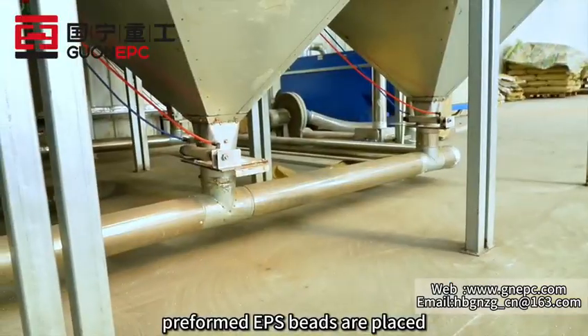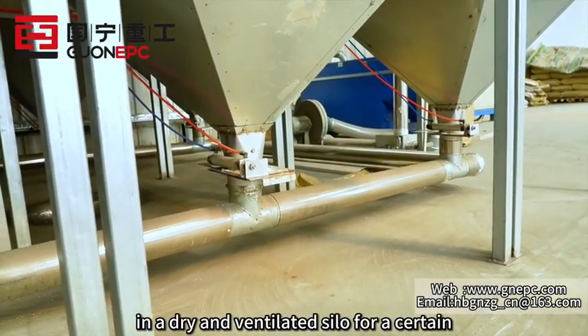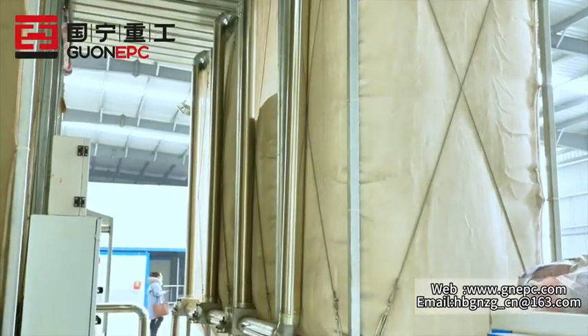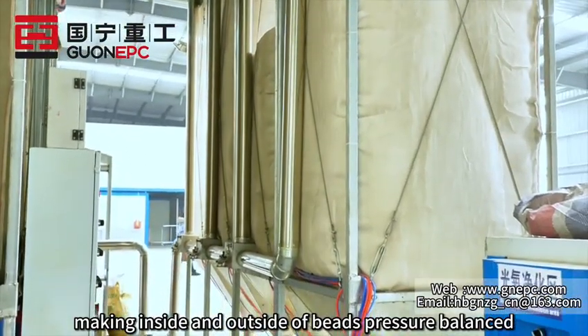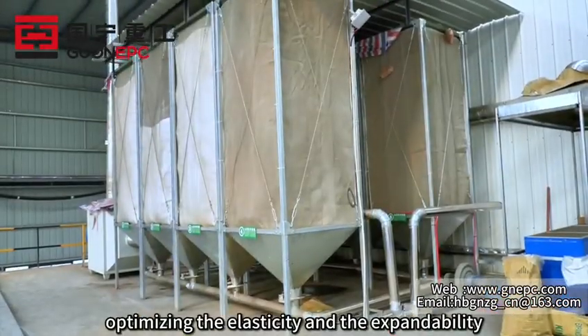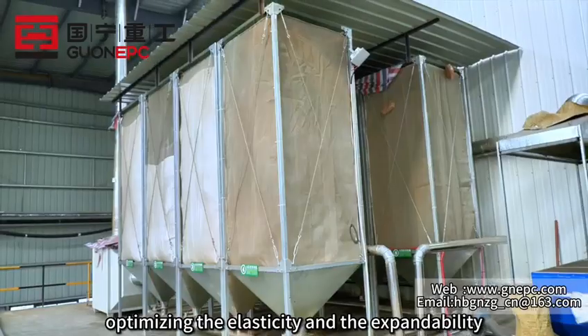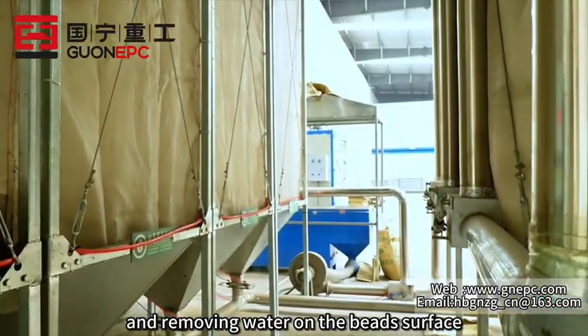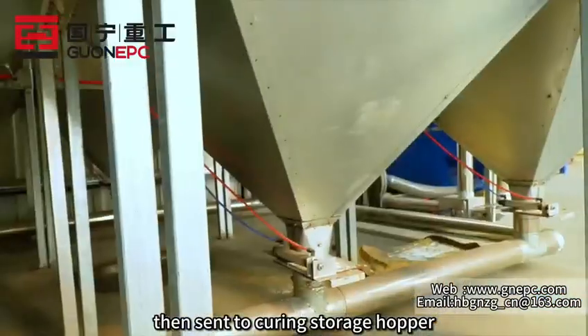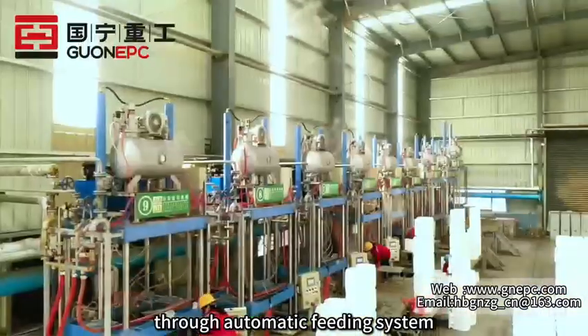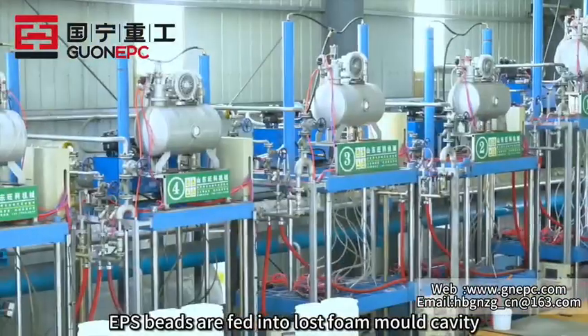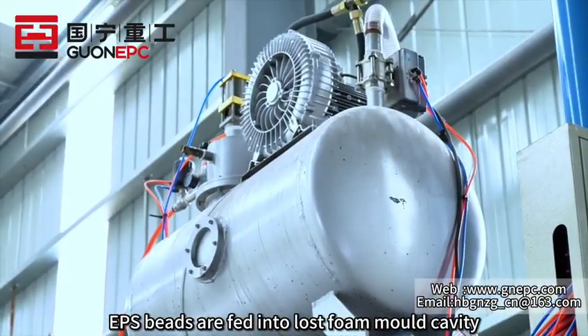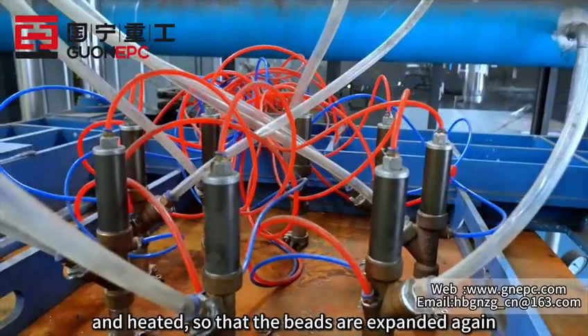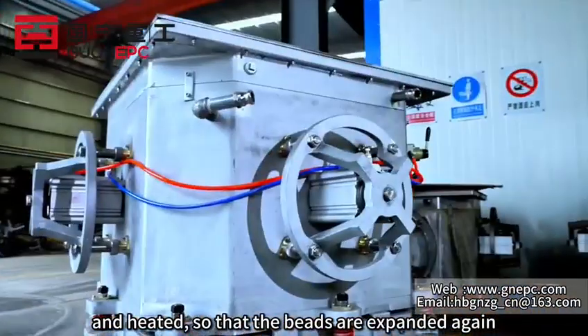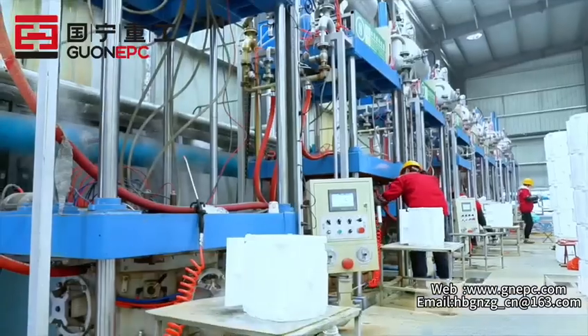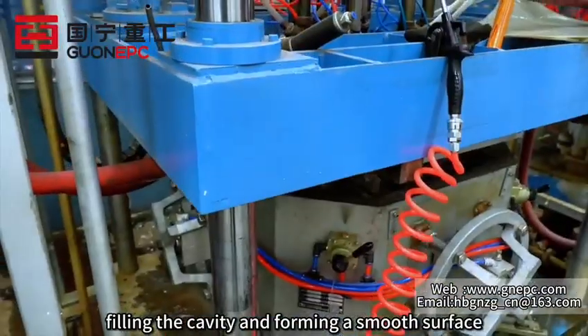Pre-foamed EPS beads are placed in a dry and ventilated silo for a certain period of time, making the pressure inside and outside of the beads balanced, optimizing the elasticity and the expandability, and removing water on the beads' surface, then they go to curing storage hoppers through an automatic feeding system. After curing ripening, EPS beads are fed into the lost foam mold cavity by a pressure feeding system and heated, so that the beads are expanded again and fused together, filling the cavity and forming a smooth surface.